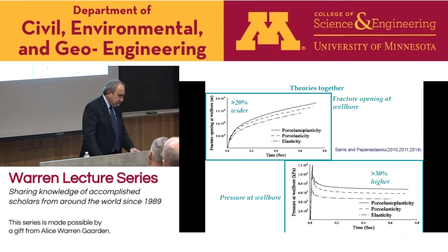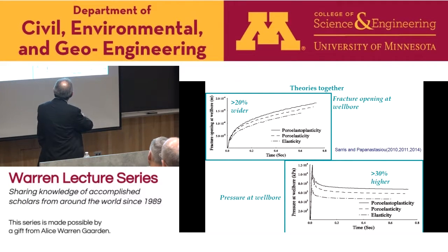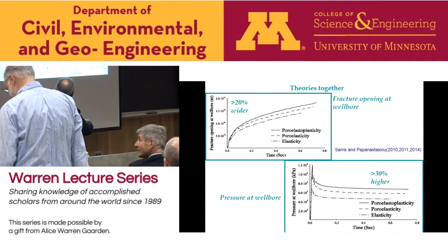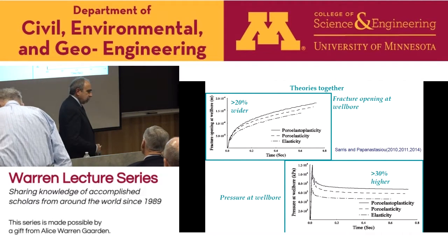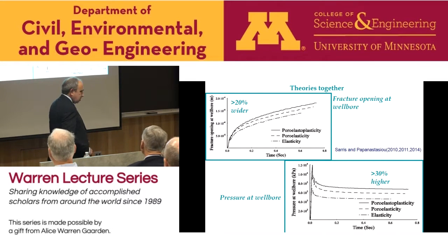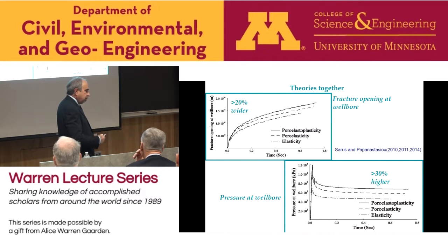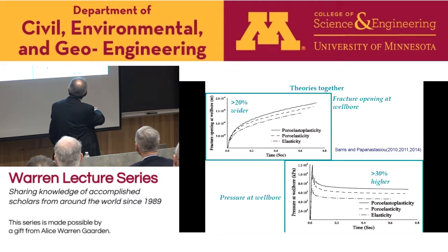And some quick comparisons. The fracture opening versus time with elasticity, poroelasticity, and poroelastoplasticity. And here actually what we found is porosity interacts with the process zone. That's the reason the fractures are wider. Some will expect narrower fractures due to the back stresses. And the poroelastoplastic is of course much wider. And some results for the pressure versus time. Again, higher pressures for the poroelastoplastic case you can see here.